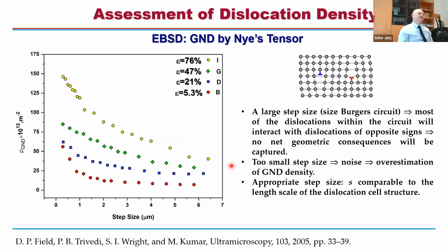Another way to estimate the amount of geometrically necessary dislocations is analyzing the Nye tensor components. Again, here you have a very similar problem. When you have a large step size, think of the Burgers circuit here, right? Most of the dislocations within the circuit will interact with dislocations of opposite signs. So if your step size is too large, like here and here, you will miss these two dislocations.